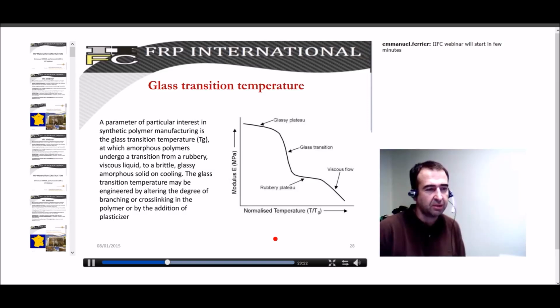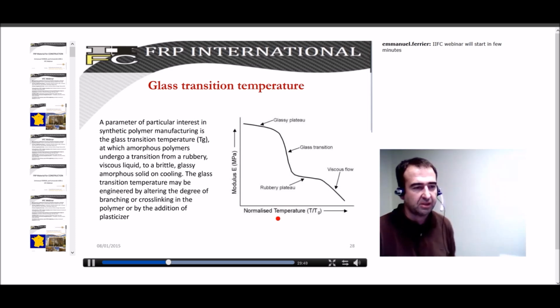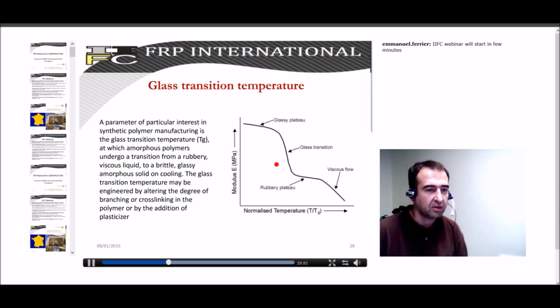The main typical property that people need to understand is the temperature sensitivity of this material. If we compare this to concrete, we know that concrete is full strength and fully hard if we mix cement and water, and the mechanical properties don't really depend on temperature. In this specific case, the temperature changes the mechanical properties of the polymer. You have a range of temperature where the polymer is thermoset with a glassy plateau where the mechanical properties, essentially Young modulus, are constant. Then there is a decrease, to get the rubbery plateau where the properties exist but are very low and much lower than the initial ones.